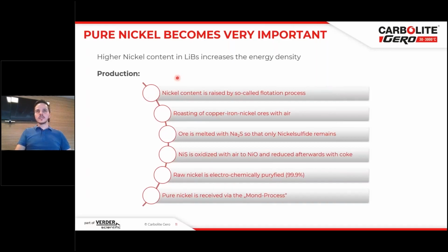So you put some chemicals into a very big pot, and you can collect the nickel raw and ore material from a surface. This you put into a roasting process with air to get a kind of copper iron nickel roasting. The materials are converted into oxide salts. Those salts are then melted together with sodium sulfide. So this is a separation process in which the copper and the iron are separated from the nickel so that the nickel sulfide remains.